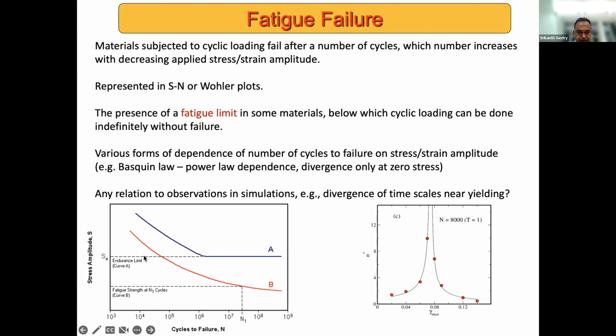And what you see in this diagram in the blue curve is that there is a stress amplitude below which the number of cycles needed to fail diverges. Okay, it's not drawn in a very nice way, but you can make a comparison with what we've discussed earlier, where we said that under cyclic shear deformation, the number of cycles needed to reach the steady state diverges at the yielding transition. Okay, so there's a couple of associations one has to make.